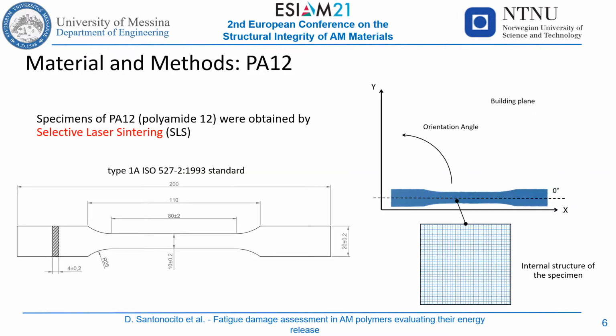The material under study is a polyamide 12, which has high mechanical properties, good chemical resistance and biocompatibility. A set of 6 specimens was produced by selective laser sintering, an additive manufacturing technique that adopts a laser beam to sinter plastic or composite powder.